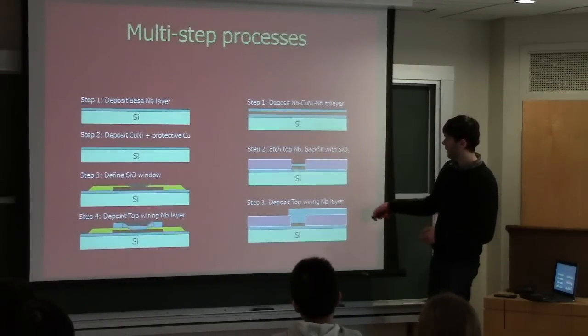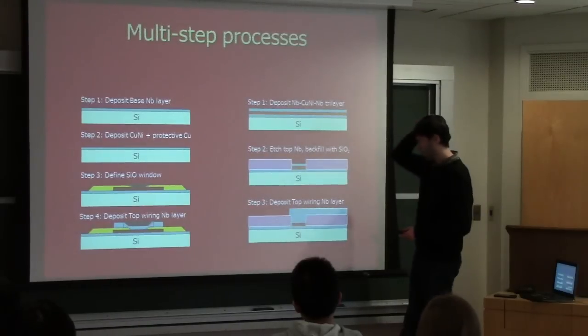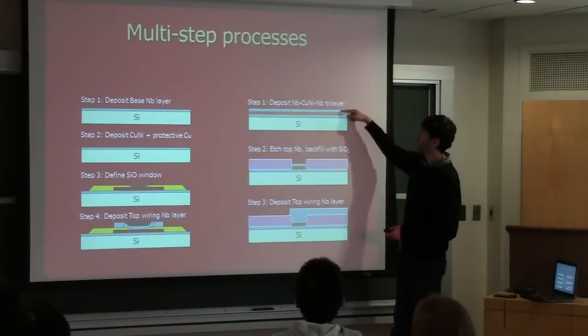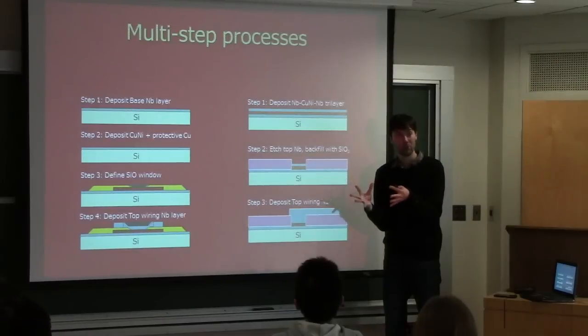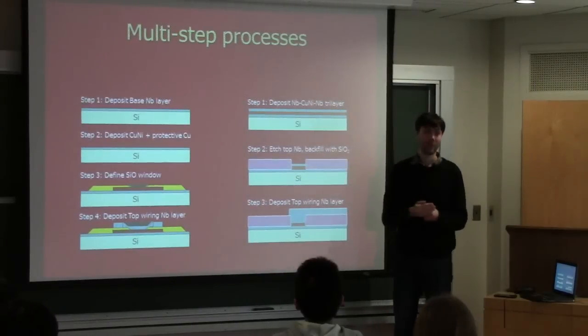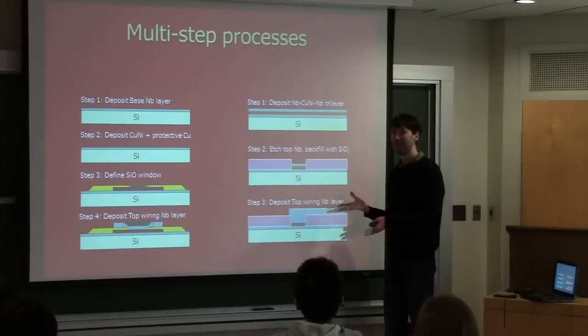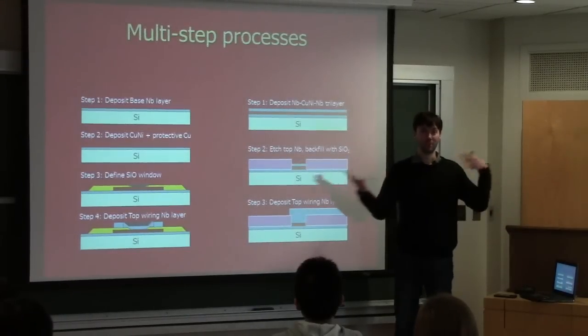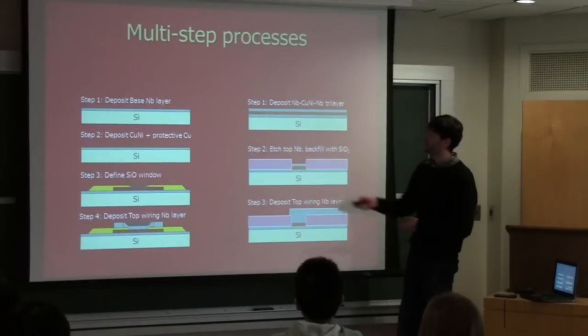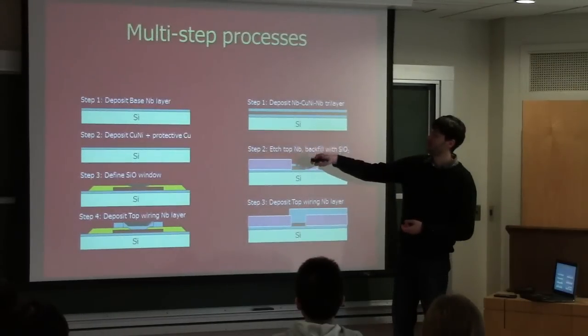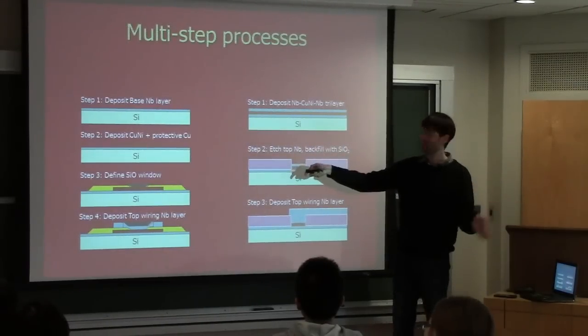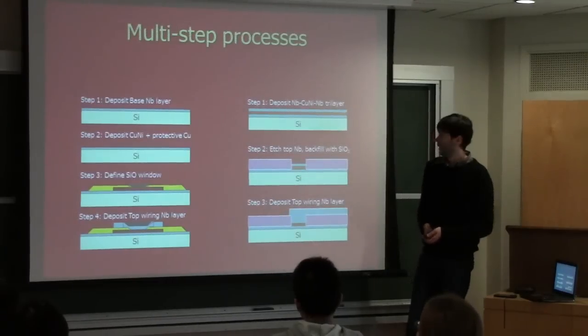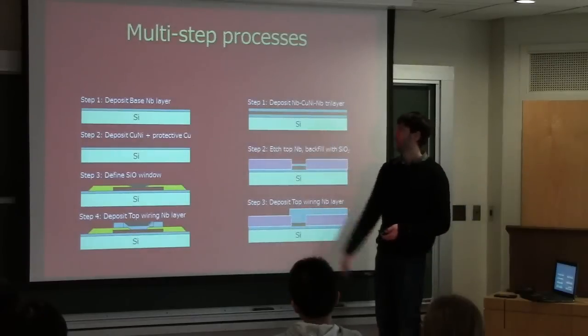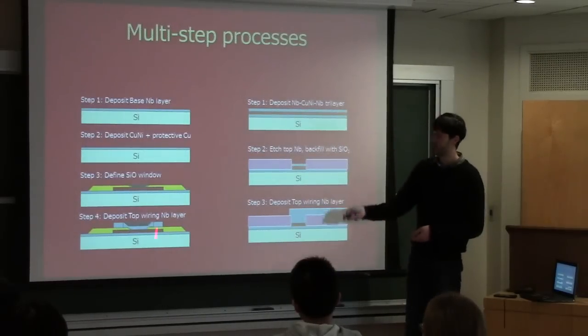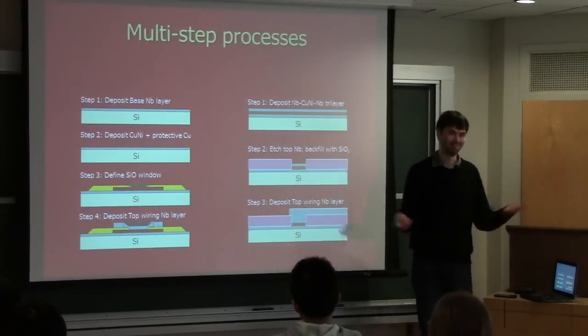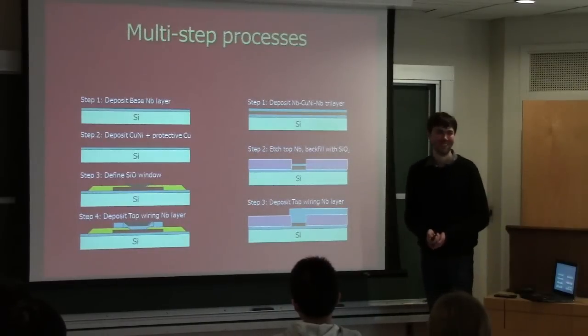Well, this was a smarter route because here all of these three elements are deposited in one vacuum cycle, and so the interfaces between them are supposed to be very clean, because every time you take the thing out of the machine and expose it to air, you can contaminate. So you can see here the first layer is produced, and a second layer after lithography, a third layer, etc. So this might have disadvantages, but in the end these were the samples that gave interesting physics. So how do you choose? Choose what works.